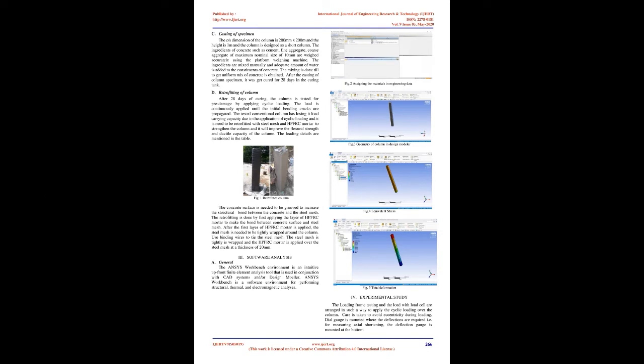size of 10 mm. Preliminary tests are carried out as per IS standard on the material used for concrete like specific gravity for cement. For fine and coarse aggregates, tests such as sieve analysis, specific gravity, impact value, crushing value are conducted as per standards. M30 grade of concrete is used for the casting of column specimen and the mix proportion is designed as per the standards according to the values which are arrived in the preliminary test. The mix proportion for M30 grade of concrete is 1:1.52:2.94. B. Retrofitting materials. In this paper, the materials used for retrofitting are steel mesh and HPFRC.